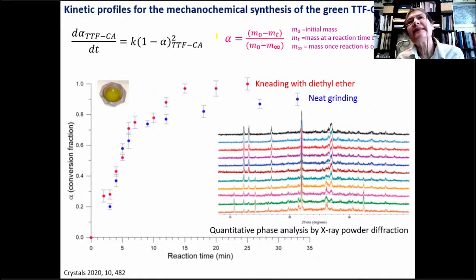Then after this, I decided to study the kinetics of the formation of the green tetrathiafulvalene chloranil form. We studied that using quantitative phase analysis from laboratory X-ray powder diffraction. And we determined a second order rate law for the neat grinding, so for grinding in absence of liquid additives. By forming pastes with diethyl ether, we found that the reaction occurred overall faster, but the kinetic model was different.